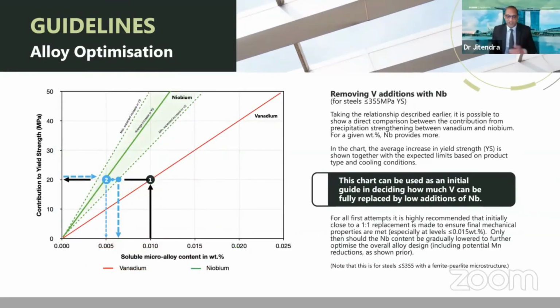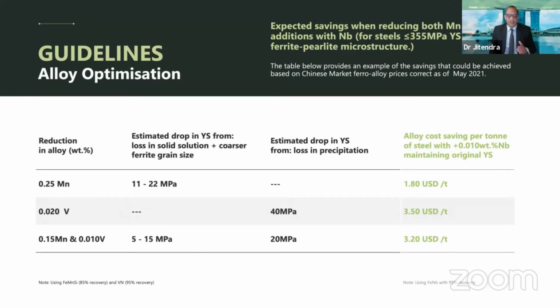Similarly, there's a different chart here that we've put together for vanadium. And as you can see, niobium effectively has twice the potency of vanadium, so we're able to literally make half that addition. This summarizes the reductions in alloying content and the strength drop we'd expect if you took out, say, 0.25 manganese here or 0.02 vanadium, and what the addition of 100 ppm niobium, so the ultra-low niobium addition, would do to compensate with respect to price. You can see here in these three examples there are net savings to be made, ranging at the moment from $1.8 to even $3.5, depending on how you substitute the manganese and vanadium content.